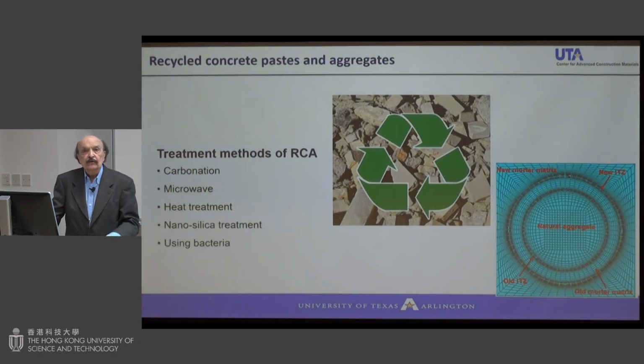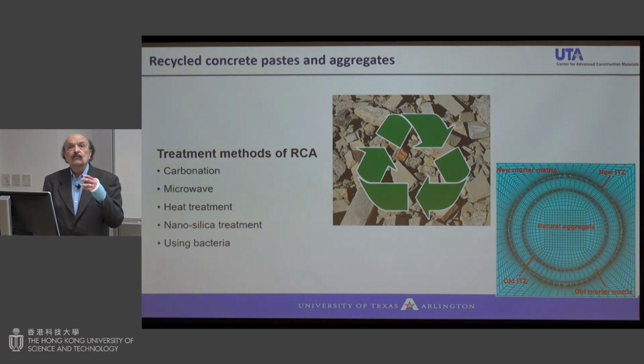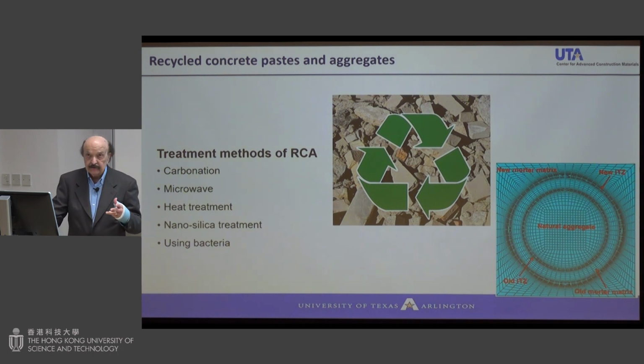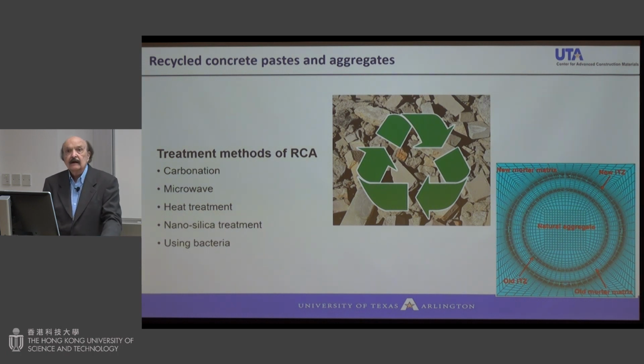So we all know that concrete waste, whether after the demolition or after the earthquake, or from the ready-mix truck when it comes back and is cleaned, there is a lot of concrete that can be recycled. Currently, recycled concrete aggregate is really not used for structural concrete, and the reason is that when you crush it, it has this thin layer of mortar which is very porous. So it absorbs a lot of water, and as a result, when you replace natural aggregate with recycled, you can control the strength, but durability because of this weak interface is a big issue.